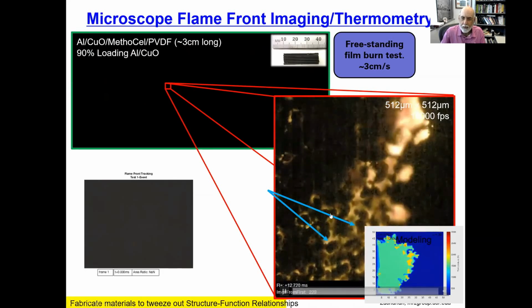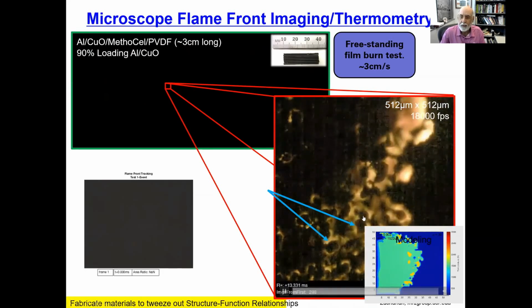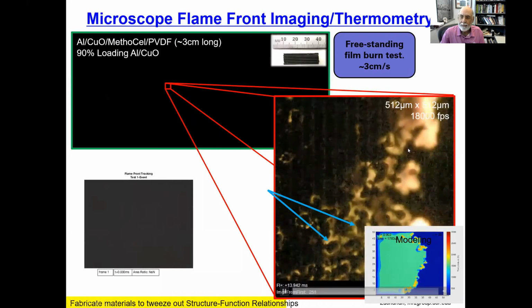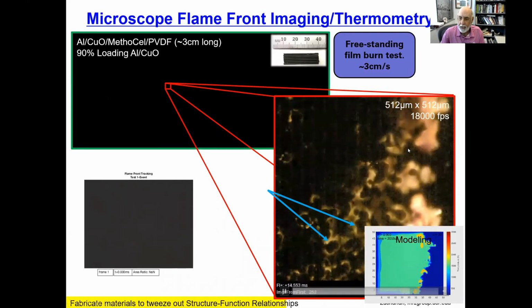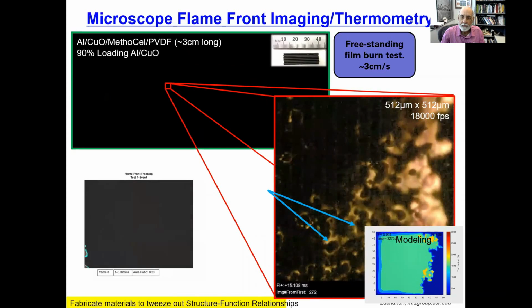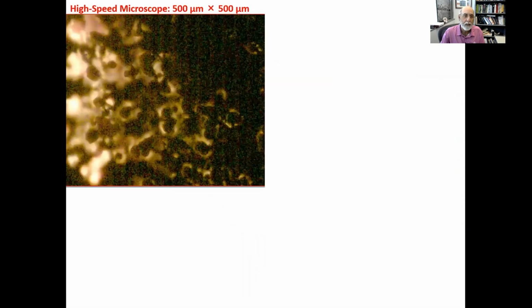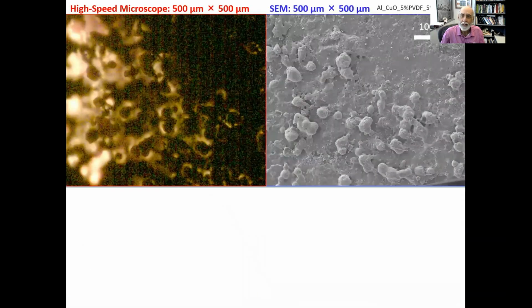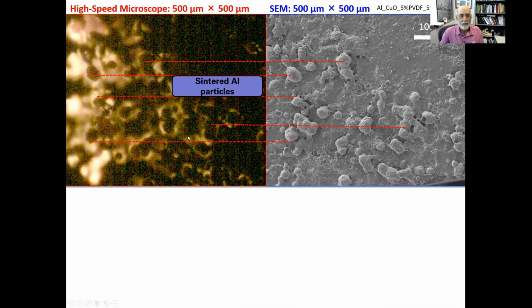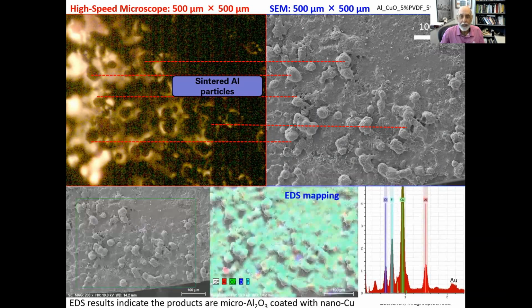So we can track what's going on, and we can do post-inspection of these materials after the fact to see what we left behind. So this is what we left behind, and then we can actually find exactly that material, exactly those positions. So this particle here is that particle there under an electron microscope, and then we can do post-interrogation to get things like compositional mapping, et cetera.